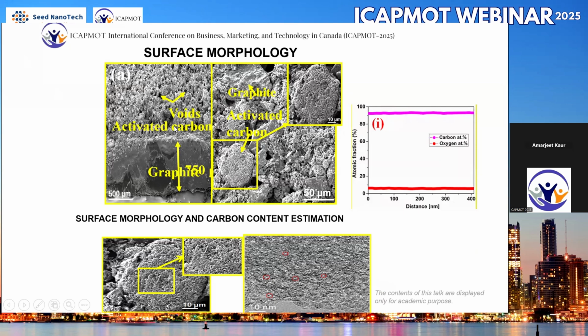So basically, when we developed the electrode, we developed it on the graphite sheet. For making the device, we put the slurry of this activated carbon on the graphite sheets. So this is the graphite layer which you can see, on which is the activated carbon, and you can see the voids in this activated carbon.